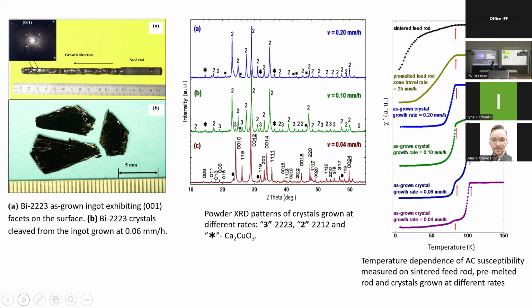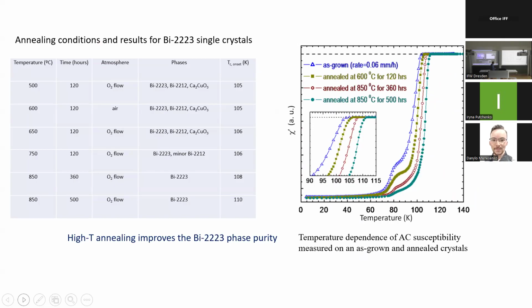And these two pictures show the effect of pulling rate on the phase purity, or the crystal purity. The best crystals are prepared at 0.04 millimeter per hour, but still there is a small kink around 80K. It means that we still get about 2-3% of bismuth 2212 phase. We could improve the phase purity of the samples by high temperature annealing at 850 degrees in oxygen flow. By X-ray diffraction, we get impurity-free crystals.